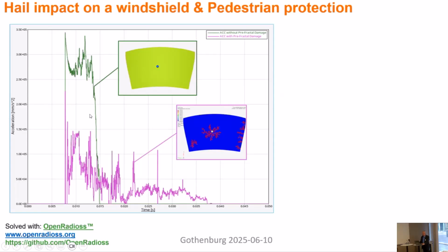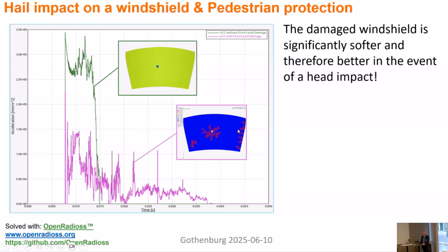And then we validated, which is important for pedestrian protection, for example, the acceleration which you will measure, or the head will measure, the pedestrian protection head. And for this, let's say, virgin glass, we see a high acceleration or deceleration, whereas for the pre-damaged glass, much lower, which is better for the occupant, but for sure not so good for the windshield itself. The damaged windshield is significantly softer and therefore better in the event of a head impact. This is good, but who wants to drive with a damaged windshield?